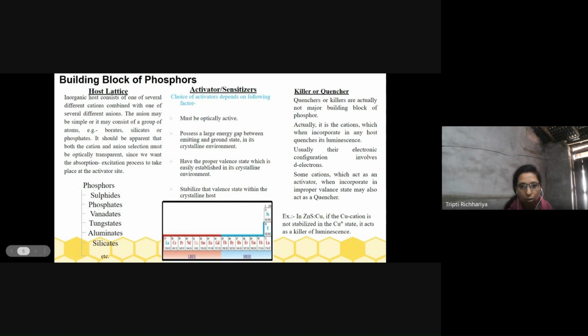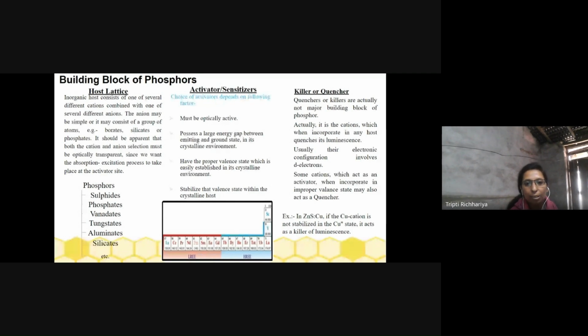The next building block of the host lattice is the activators or co-activators. The co-activators are also known as the sensitizer. For choosing the co-activators or activators, it should always be kept in mind that the activator must always be optically active, because the overall absorption and the emission take place at this lattice site. There is a wide energy gap between the emitting and the ground states within the crystalline host, so that we can receive large energy.